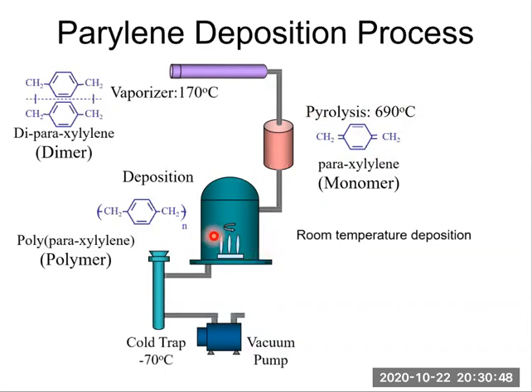deposit on the wafer surface and other exposed surfaces, forming parylene film. But note that the deposition occurs at room temperature. So this deposition chamber is at room temperature, even though the pyrolysis occurs at 690. But the deposition occurs at a much lower temperature. Room temperature.